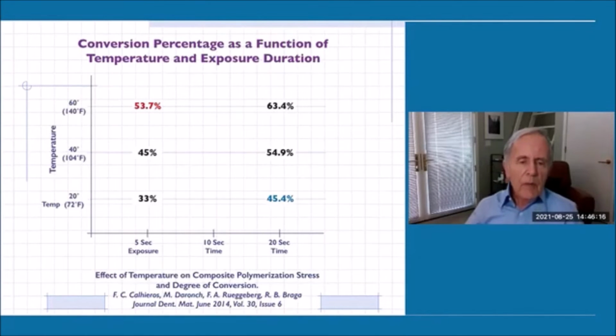This was a study by Braga and Rueggeberg on the effect of stress and temperature on the degree of monomer conversion. They took two different conditions. One sample was cured for 20 seconds at room temperature. You see that on the right. And another sample was cured for 5 seconds, but it was warm. You see that on the left.